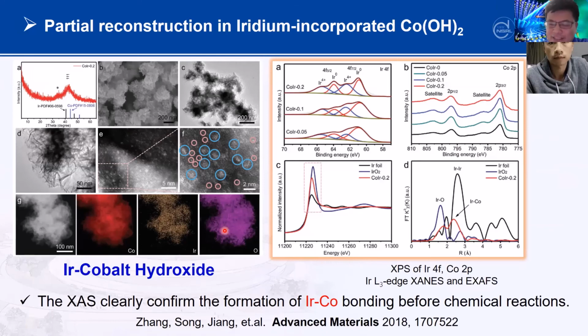Since, as I mentioned, the soft X-ray work I did is mostly located at the XMCD endstation in Hefei Light Source. As I mentioned on the first slide, Hefei is about a 2-hour fast train from Shanghai. Shanghai has the third generation hard X-ray light source, with an energy of about 3.5. That means the sample is the same and the reaction is the same. So we always synthesize the control sample, the typical model catalyst, which can combine the soft X-ray with the hard X-ray.